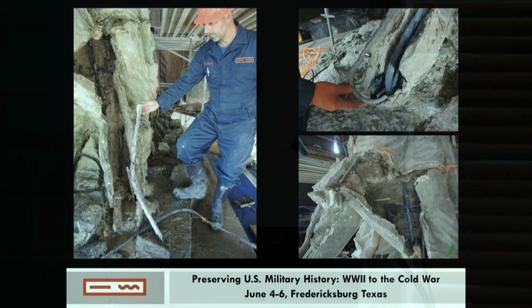After treatment of the rebar, all excavated areas were treated with Cortec Migrating Corrosion Inhibitor 2020. This is designed to penetrate through cementitious materials, including concrete and mortar. We put this everywhere, including all parts of the sculpture which were not opened. It's targeted to go in and reach the rebar that we could not reach.